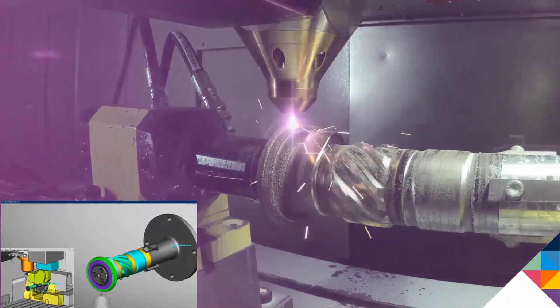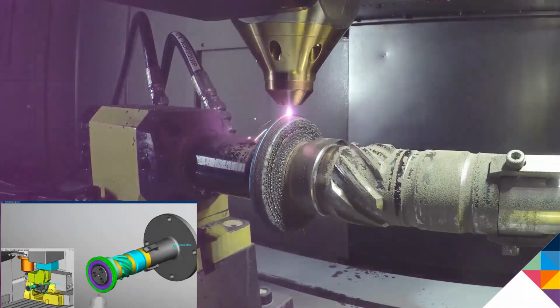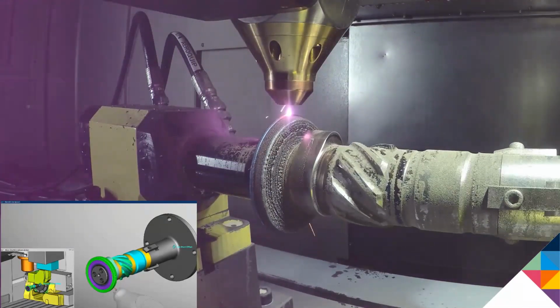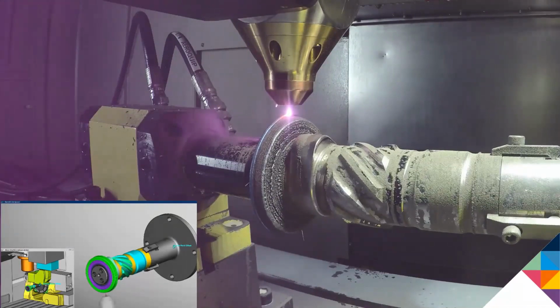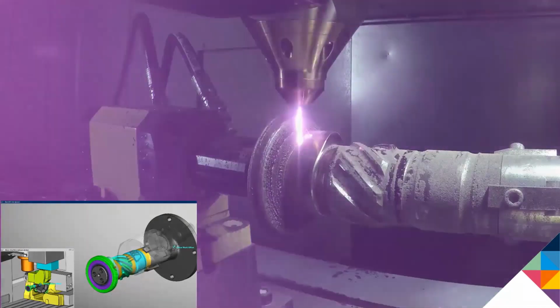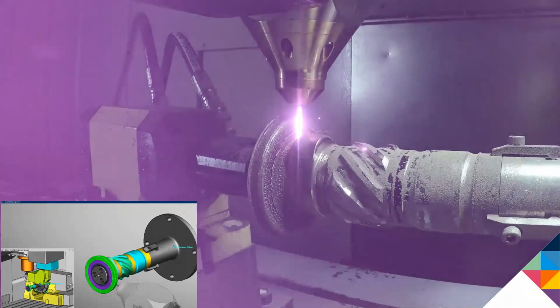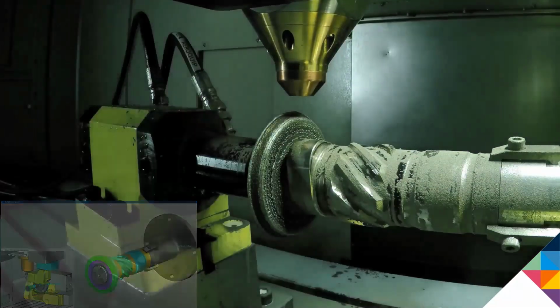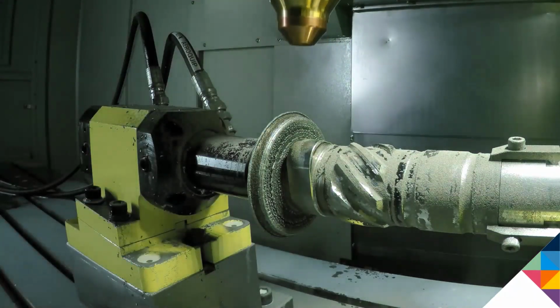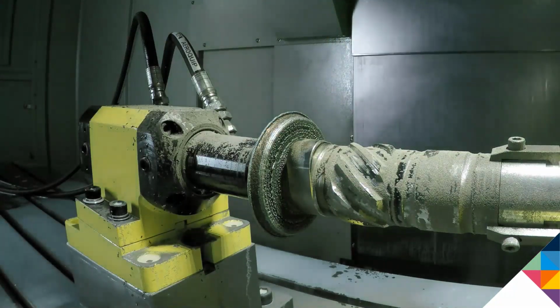You can see in this that it is still forming a sort of conical shape. We believe that is an issue with the step over, or the step up rather, on the tool as it steps up in between the layers. It again uses a helical wraparound, and this is something we intend to address on follow-up projects, developing our strategies a bit further to make sure we can build more complex features.